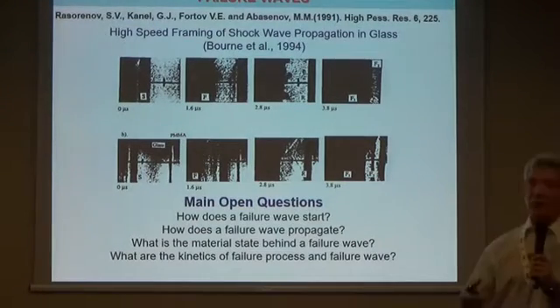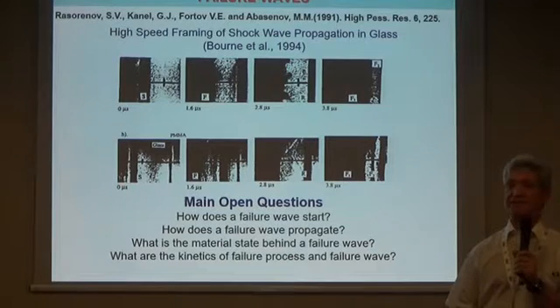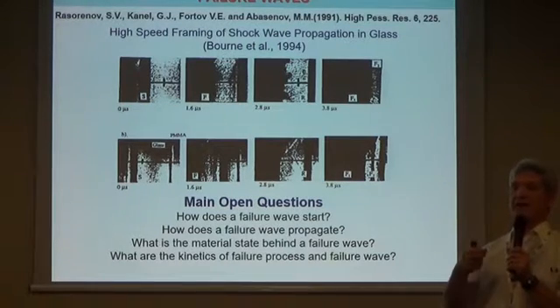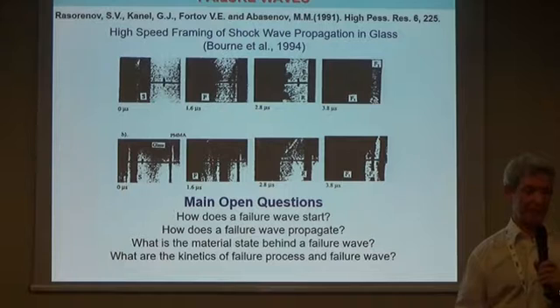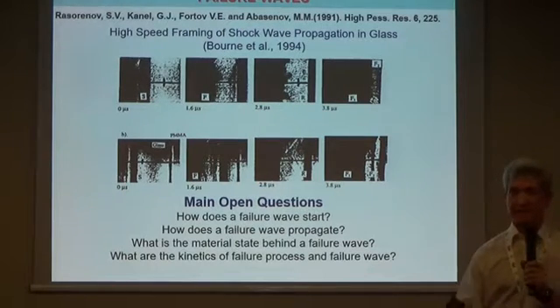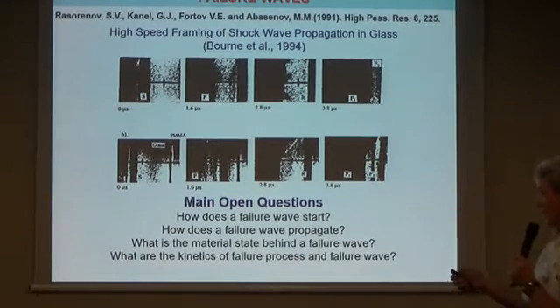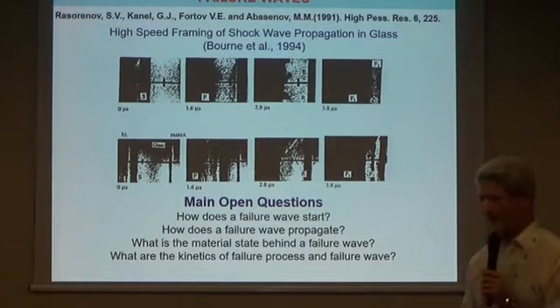Since these blow-up structures, which have the nature of the self-similar solution, represent an eigenfunction spectrum for the nonlinear problem, it means that they could be excited in some resonance region. It was very important for us to propose, from this point of view, an explanation of the failure wave phenomenon, when, due to the shock wave loading, behind the stress with some gap with the original material, we have a failure front which propagates with some characteristic velocity.